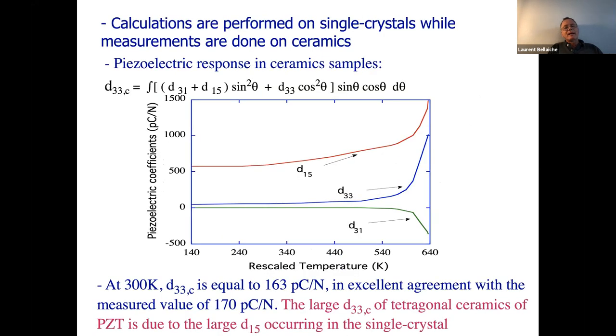And in fact, we realized that the piezoelectricity measured in PZT is on ceramic samples, not single crystal. If you are dealing with ceramic, it's a kind of average of the piezoelectric response. You do have d33 of single crystal, d31 of single crystal, but you have a third one, which is d15. And this d15 was incredibly big. If you put this d33, d31, d15 of single crystal into the formula indicated above, you get the d33 of the ceramic, and you get 163 picocoulomb per Newton, which is very, very close to the experimental value. So the effective Hamiltonian is able to reproduce piezoelectricity and also able to explain why you have such a large response. In that case, you have a huge d15 coefficient.